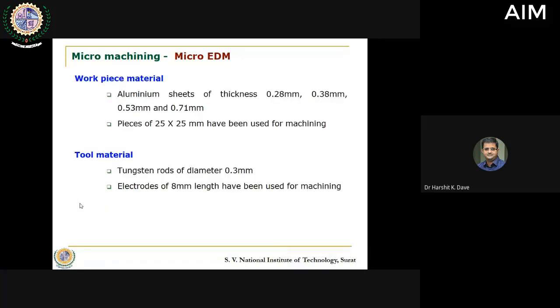Now we initiated some work on micro EDM where we wanted to carry out a drilling process initially. So what we did was we used thin aluminum sheets having thicknesses of 0.28 mm, 0.38 mm, 0.53 mm and finally 0.71 mm. All these thicknesses were in the micro domain range. These aluminum sheets were cut into pieces of 25 by 25 mm. Those sheets were cut from a larger sheet. This was required to ensure that these pieces can later be made properly flat so that there is no discrepancy in the features that we generate.